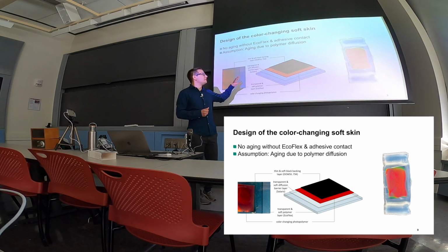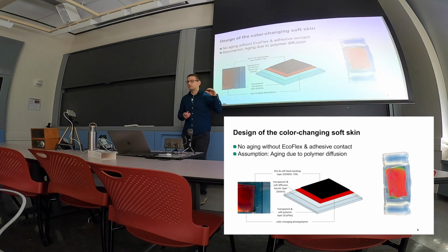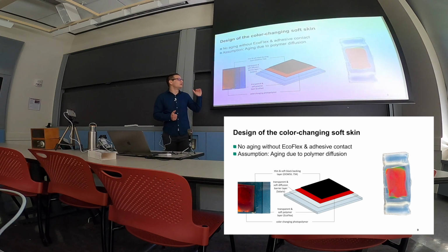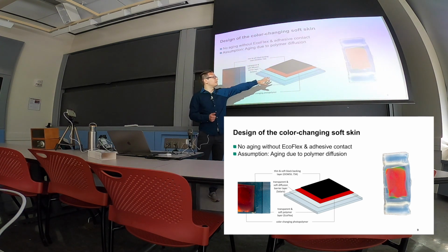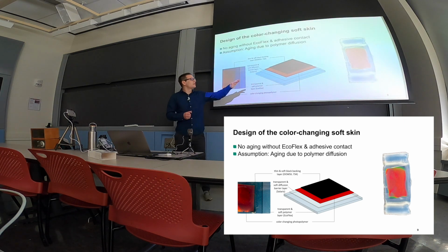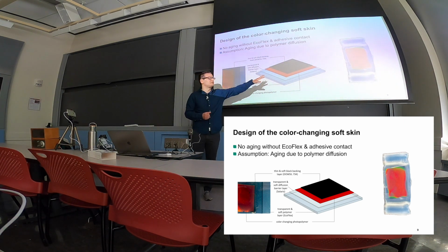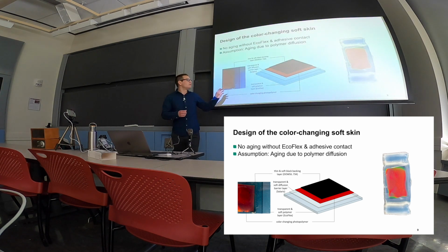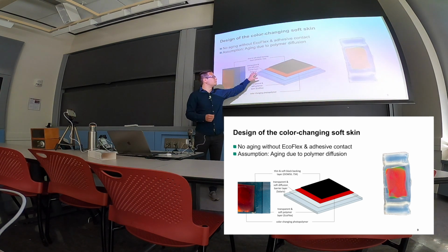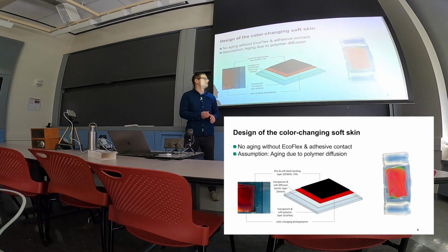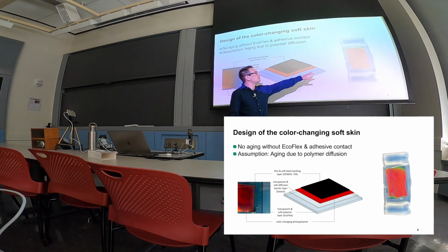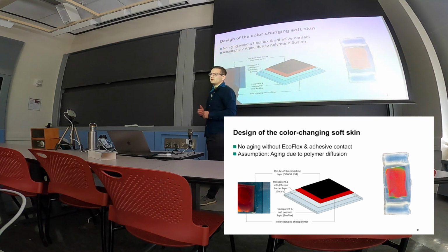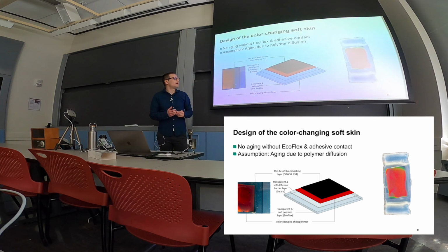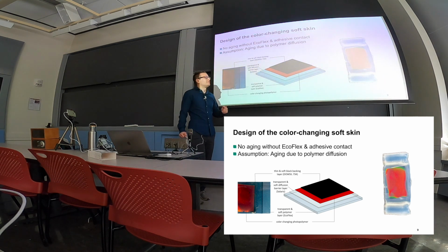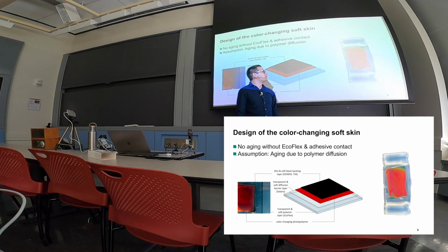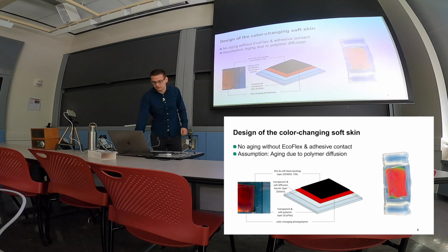I don't want to go too deep into the detail, but in the first weeks I developed a four-layer approach that was able to withstand that aging. I encapsulated the color changing material between a black backing layer to saturate the colors, and then a Solaris layer, which is a diffusion blocking layer, to stop the assumed diffusion between the particles inside of the Ecoflex and the color changing material. And we can see with this approach here on the right side, I was able to realize such a soft robotic system, which at least for the human eye did not age that quickly anymore. And we can look through the whole system on top of the color changing material and still see the sensor being in there.